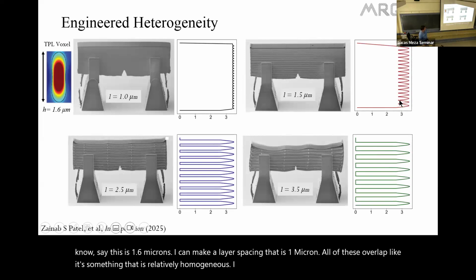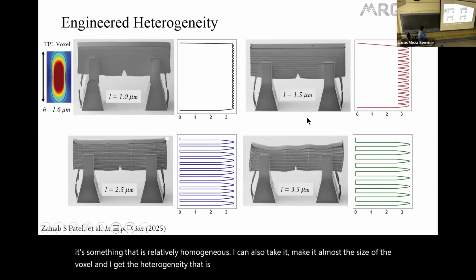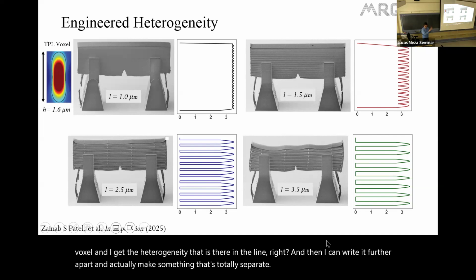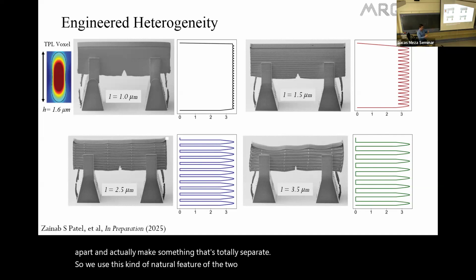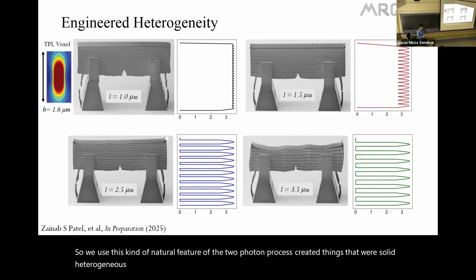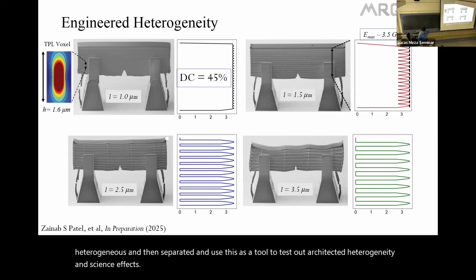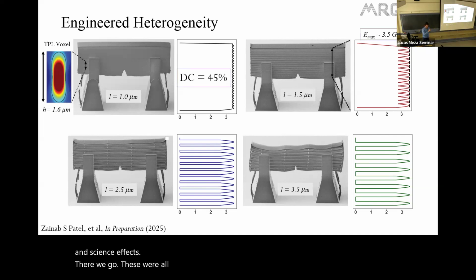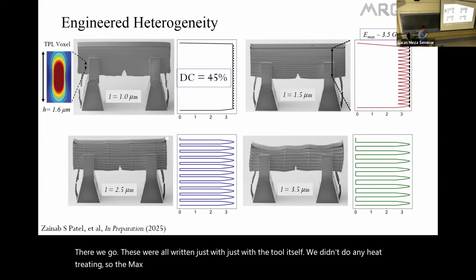I can also make it almost the size of the voxel, and I get the heterogeneity that is there in the line write, and then I can write it further apart and actually make something that's totally separated. So we use this natural feature of the 2-photon process, created things that were solid, heterogeneous, and then separated, and use this as a tool to test out architected heterogeneity and size effects. So there we go. These were all written just with the tool itself. We didn't do any heat treating, so the max degree of conversion was 45%. So somewhere not super, super brittle like the heat treated ones were, but not very ductile.